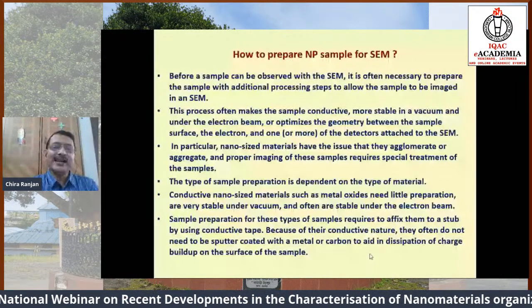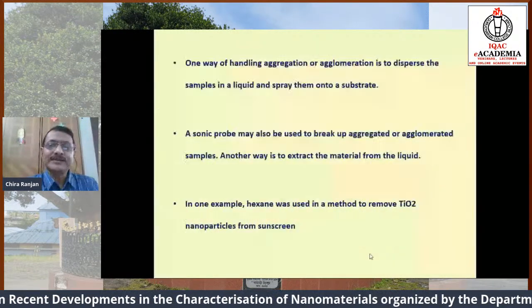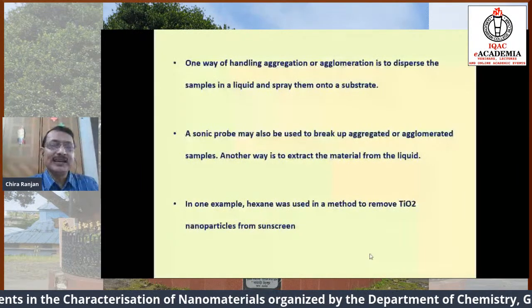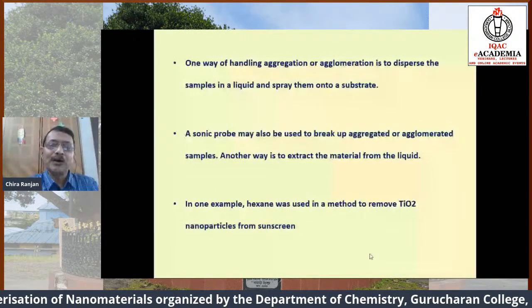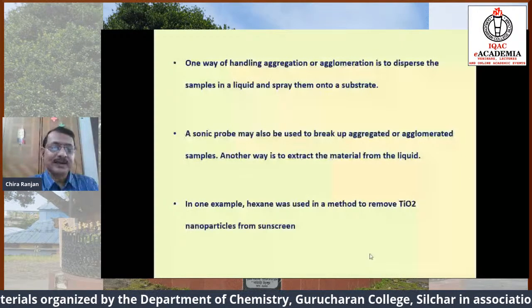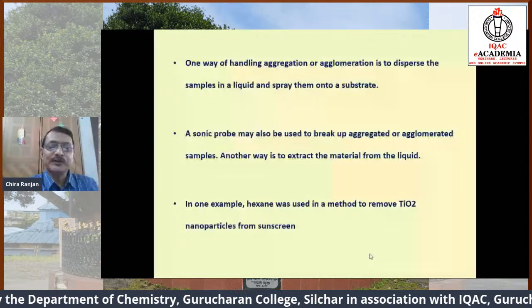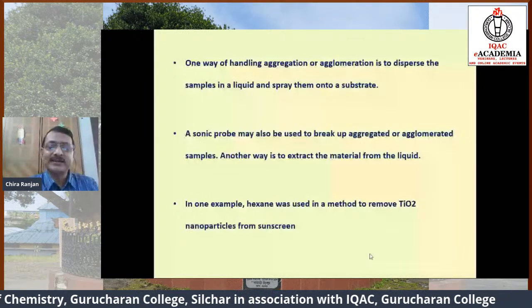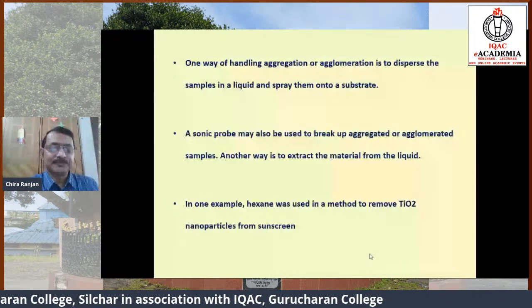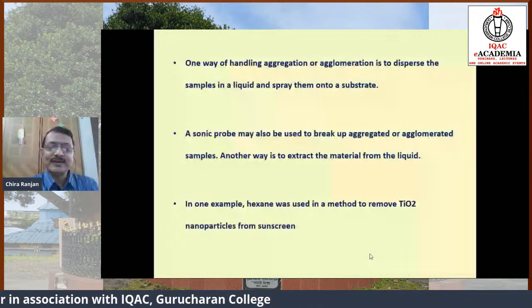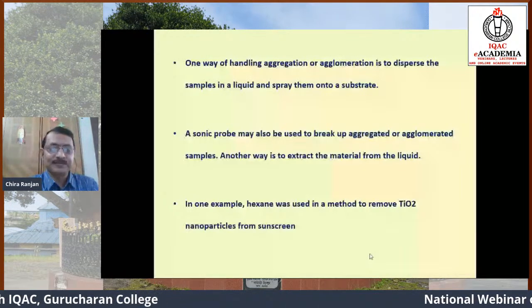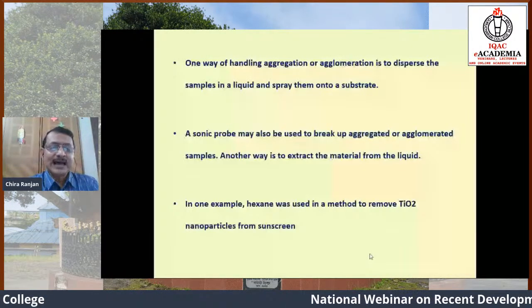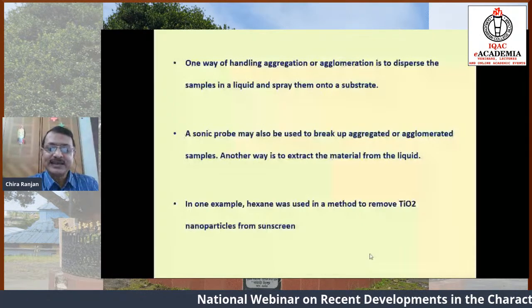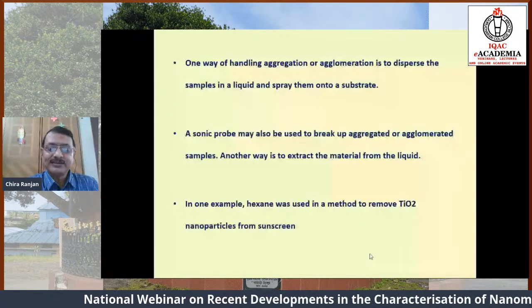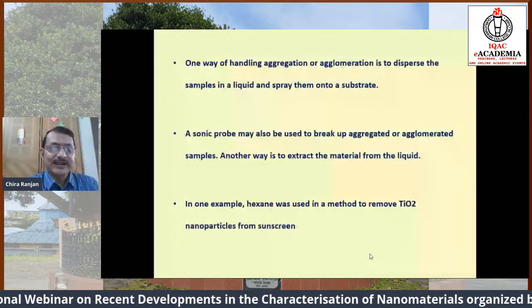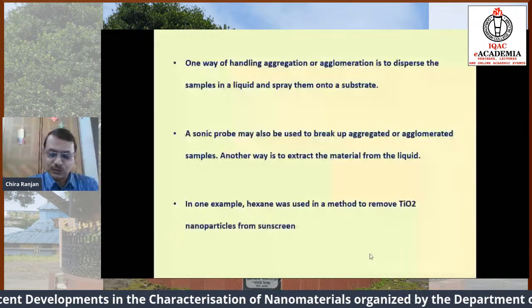One way of handling aggregation or agglomeration is to disperse the sample in a liquid and spray it onto a substrate. A sonic probe may also be used to break up aggregated or agglomerated samples. Another way is to extract the material from the liquid. In one example, hexane is used in a method to remove titanium dioxide nanoparticles from sunscreen lotion.